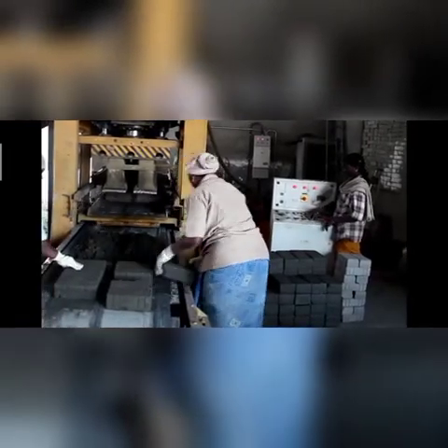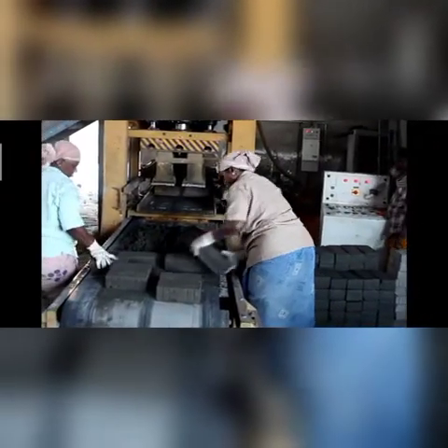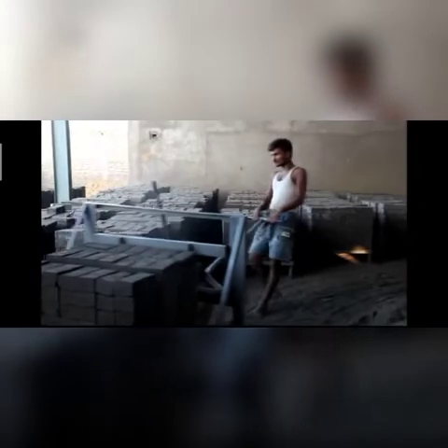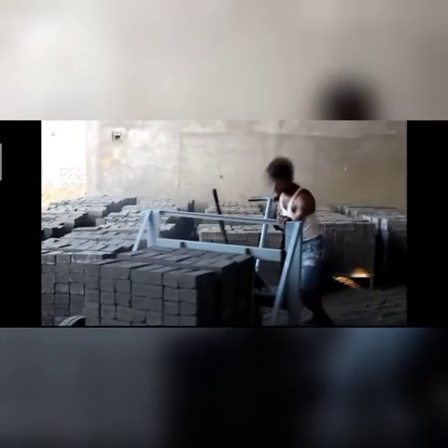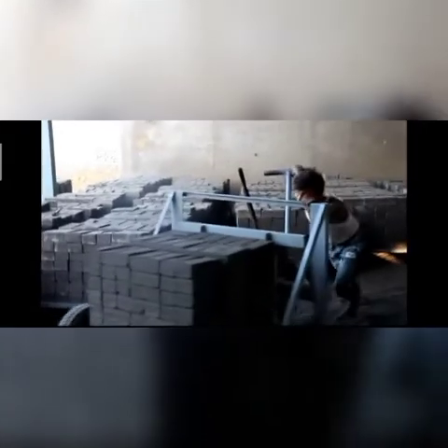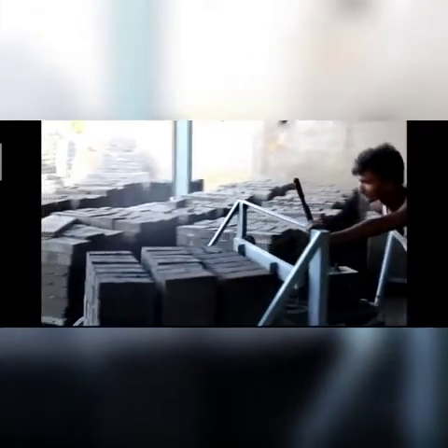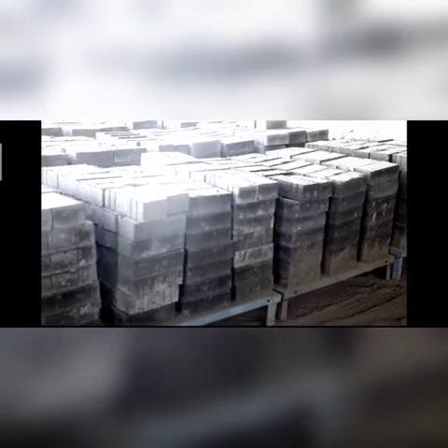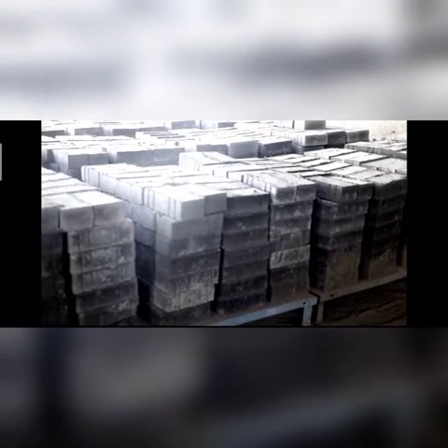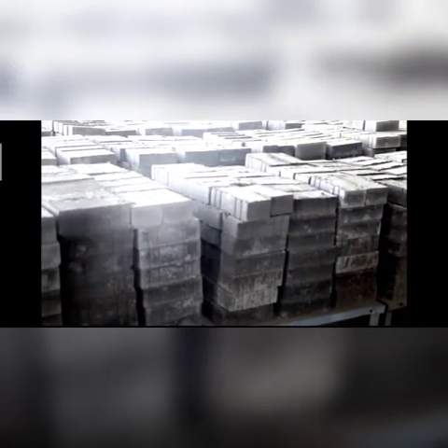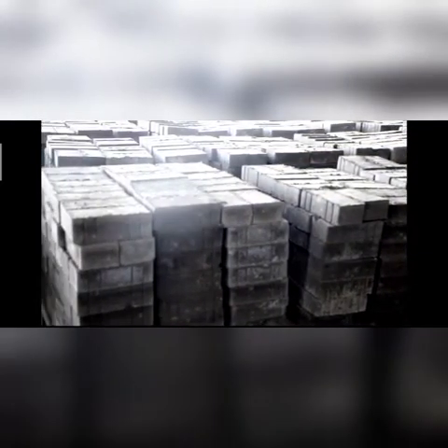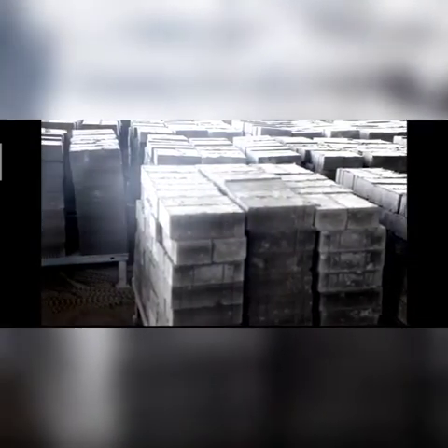The pressed bricks are taken manually and laid on wooden pallets in 4 to 5 layers. Pallets should be strong enough to carry the stack of green bricks without sagging. Bricks laid on pallets are transported on a hydraulic trolley from the press area to the stackyard. Green bricks shall be air-dried for 1 to 2 days. Thereafter, air-dried bricks should be water-cured for a minimum period of 14 days. Curing is carried out by sprinkling of water manually or by any other method. The curing period may be extended during cold and wet weather.